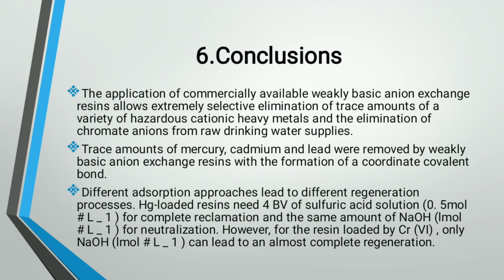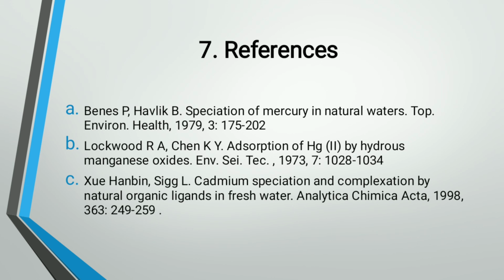Mercury loaded resins need 4 BV of sulfuric acid solution for complete reclamation and the same amount of sodium hydroxide for neutralization. However, for the resin loaded by chromium, only sodium hydroxide can lead to an almost complete regeneration.